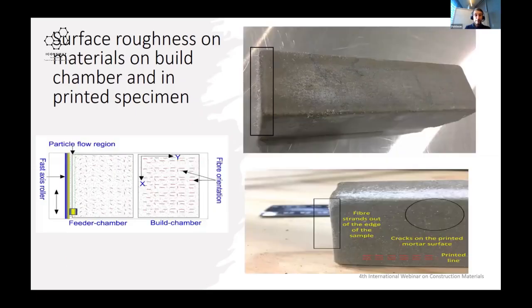Once we printed, we also saw that about 70 or over 70% of the fibers are parallel to the y-axis, and less than 30% are in the x-axis. So basically, with most of the fibers in the y-axis, when we test mechanical properties, the bond of the material is much stronger in the y-axis compared to the other axes. All right, so this is enlarged here, and we can see the fibers coming out from the printed specimens.